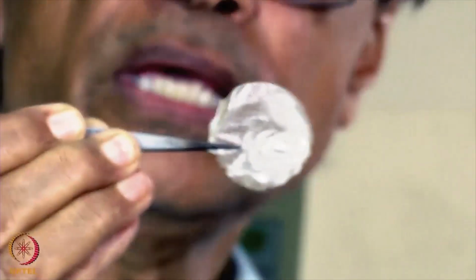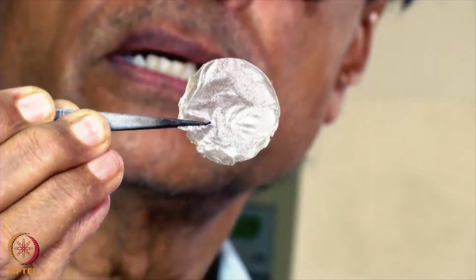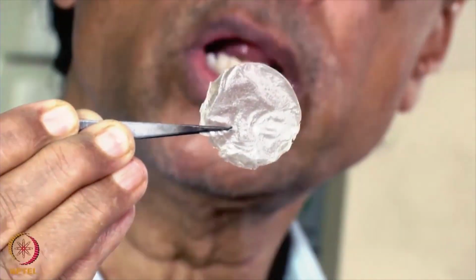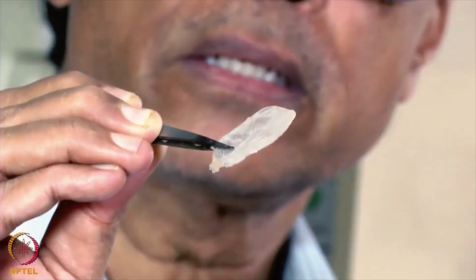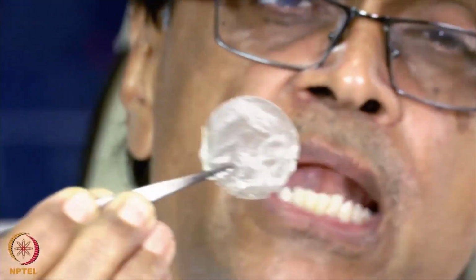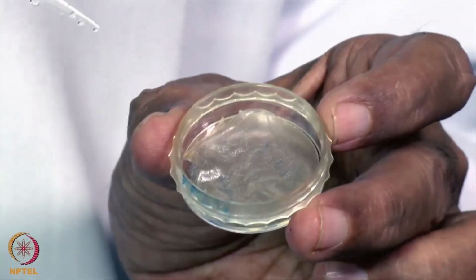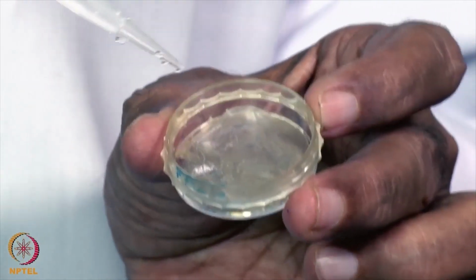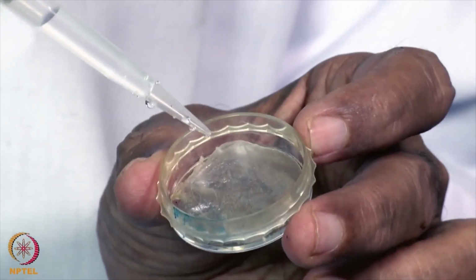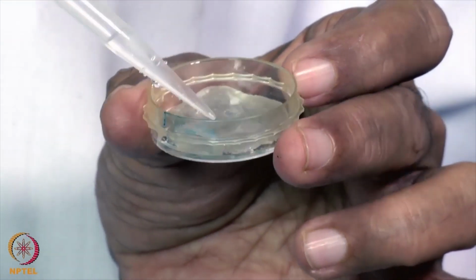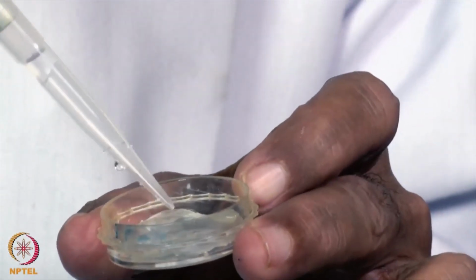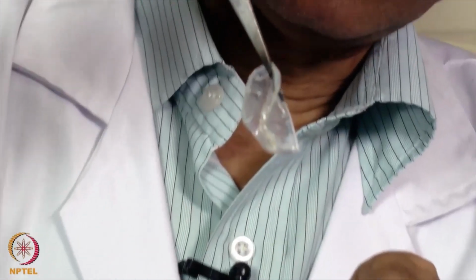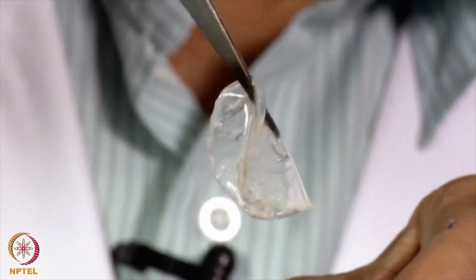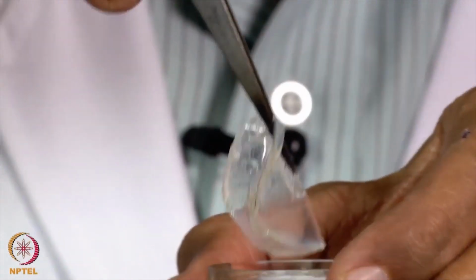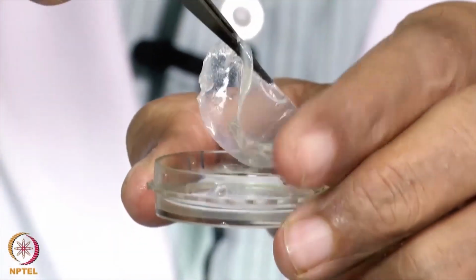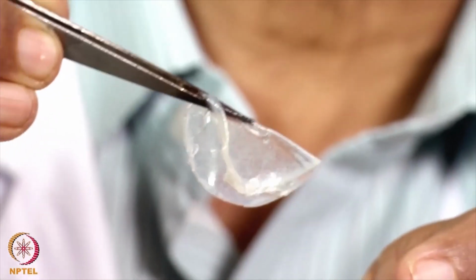As you can see, this is the glutaraldehyde cross-linked iota carrageenan cyclic beta glucan, in the ratio of 75 to 25. We call this hydrogel because it will swell when we add water to this. When we add water to it, it should retain water and swell. That is why it is called a hydrogel. As you can see, the gel has swollen, taking up a lot of water, and this property helps in designing wound healing patches with this carrageenan and beta glucan.